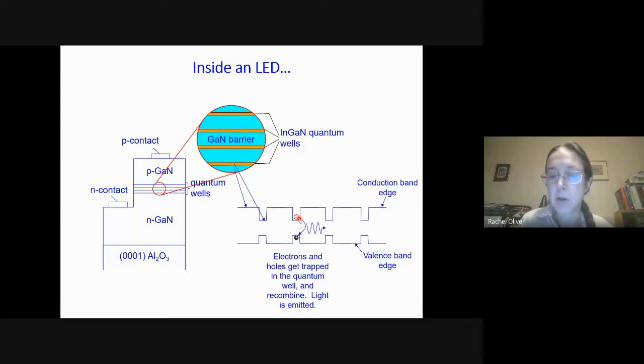And the electrons and holes are trapped, recombine with one another, and as the electron loses energy as it combines with the hole, that energy is given out as photons, light, with a wavelength which is characteristic essentially of the band gap of the indium gallium nitride. Now, the point of the quantum wells is to force the positive and negative charge carriers together into a really narrow region or really small volume of the material. That makes it much more likely they'll combine to give out light.